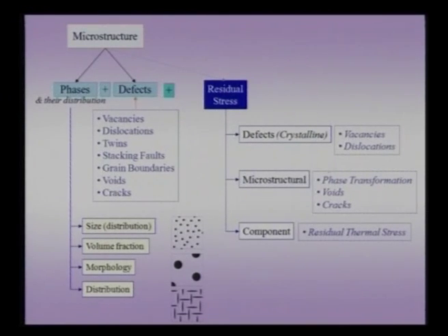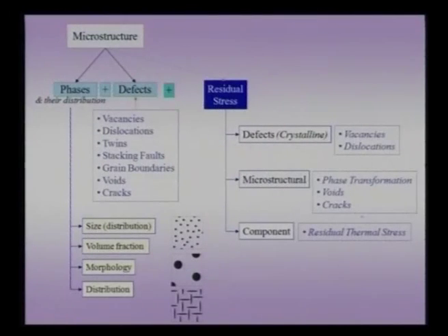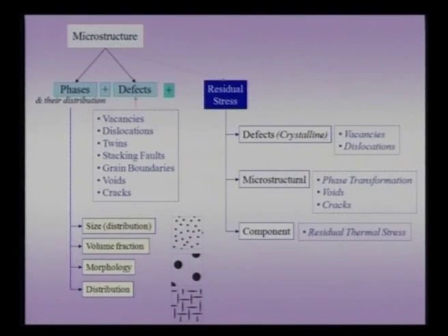Residual stresses can come from processes like phase transformations. They can be because of voids and cracks — voids and cracks themselves are not sources of residual stress, but if you have a far-field stress, it can be amplified by voids and cracks. Even making a simple component like a slab of material, you could have residual thermal stresses, which I have also pointed out could be intentionally introduced for beneficial purposes.